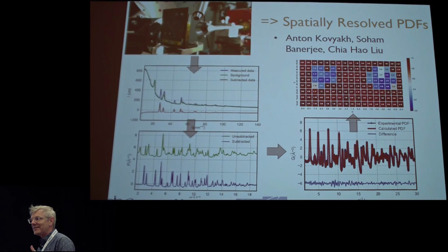Once you can do normal incidence thin film PDF, we can imagine doing lab-on-a-chip experiments where we make a chip that has different compositions and different chemistries patterned on it, and we can simply measure as a function of position. So what we did here, this is a piece of carbon paper which has had different nanoparticle samples inkjet printed onto it at different locations. And then we simply do our normal incidence thin film PDF and we raster across the film and we get a spatially dependent PDF map. This is a Pearson correlation map of this showing that you have the samples here, but these are actually complete PDFs in each pixel, and we can do a fit to them and get structural information.